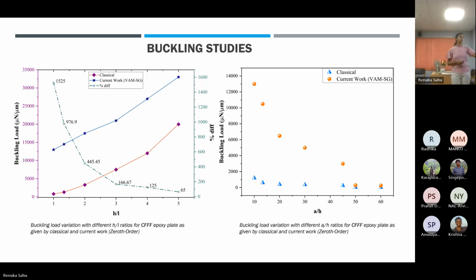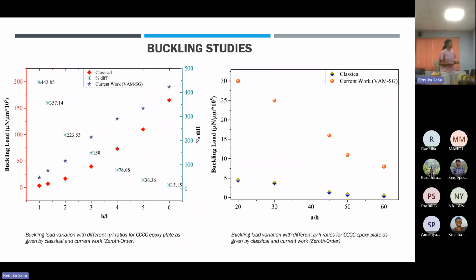Similarly, as we go for higher A by H ratios, where H is kept constant and A is varying, we can see that as the plate size increases, the difference between classical and current model goes on reducing. The same study has been done for all edges clamped also, and here too a similar kind of behavior is seen.